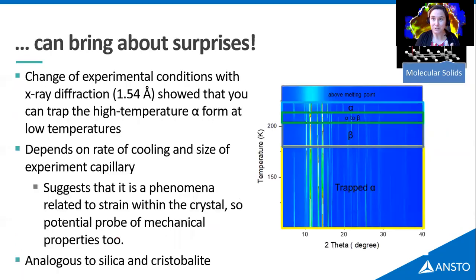But when the honours student who's working on this came to do this in the lab with X-ray diffraction, James, he found that something really strange kept on happening. As he cooled, he would actually still get the alpha form, the high temperature form, at low temperature. And it depended. He took some initiative and changed his rate of cooling. And I actually feel terrible now, I've forgotten to put the reference here. So the reference is Choi et al., in ACS Earth and Space Chemistry, published last year. And it found that this depended on the size of the capillary and the rate of cooling.